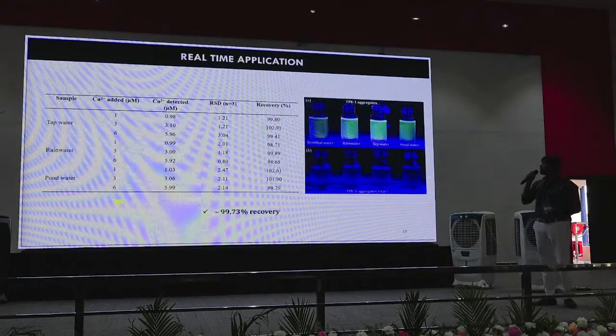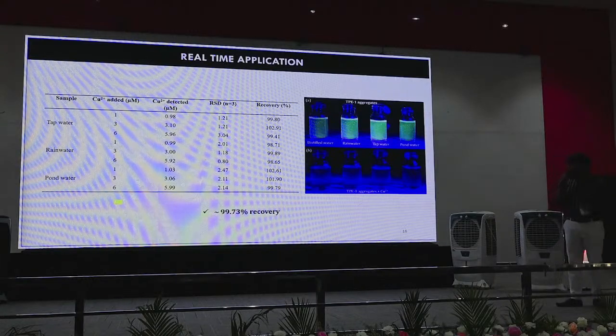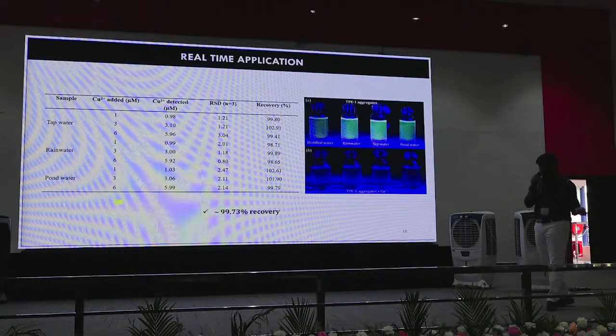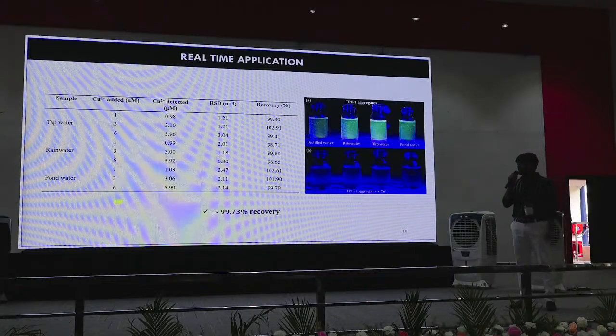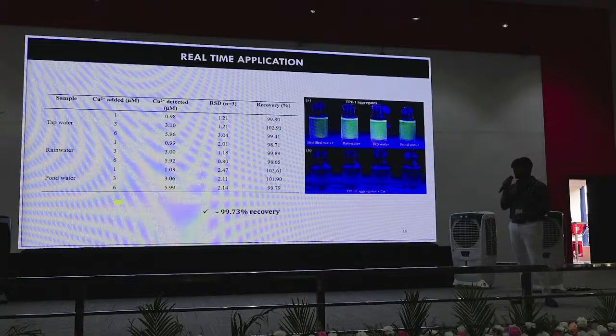And also for the real-time application, we collected samples such as rainwater, tap water and pond water. We checked for the copper percent in it, and we injected, and we found the recovery to be 99.73%, which is very good. RSD is also very good there.